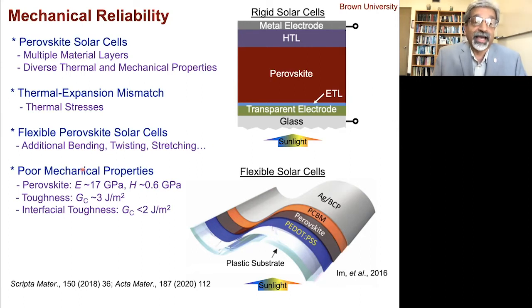And again, the mechanical properties of perovskite are actually quite poor. Again, same dichotomy: it's easier to make, low temperature melting, but then they have poor mechanical properties. The elastic modulus is 17 GPa. You may not know what this number means, but this is actually 1/10 of what silicon is. And the hardness is also about 1/10 of silicon. So they're very soft and very compliant, and they're also very brittle. They have low toughness. And interfacial toughness, for example, the interface is even lower.